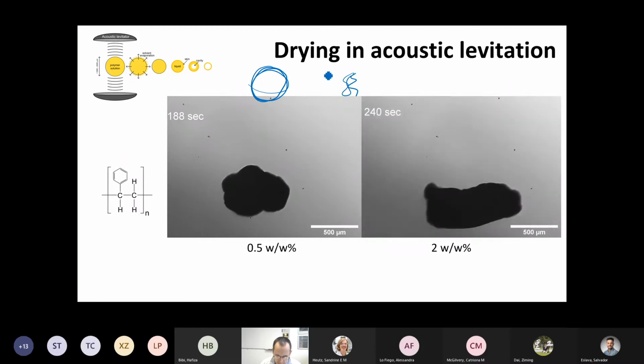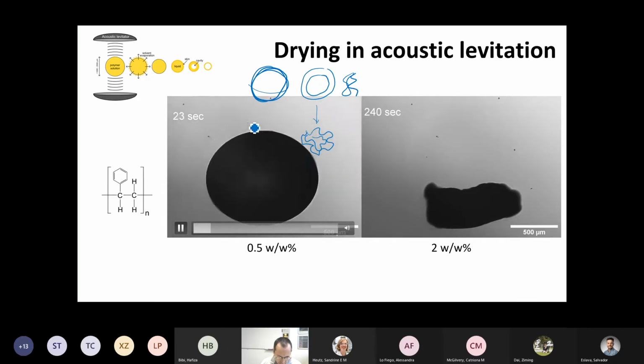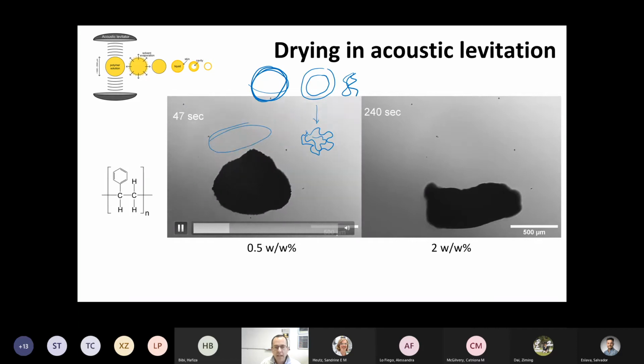Indeed, you can imagine that if you create a skin at an intermediate condition, that skin, as the particle needs to shrink further, should undulate. And so there's a buckling process that takes place. What you might have noticed as well is that as these particles dry, there were some features that emerged on the surface. You can see these were actually tiny droplets. And again, it's not necessarily surprising that there might be some kind of condensation happening at the surface or some kind of drying. I mean, let's see that in a second. And again, unsurprisingly, here taking a model polymer, just polystyrene, you see the sizes broadly corresponding to the size of the contents within the liquid.